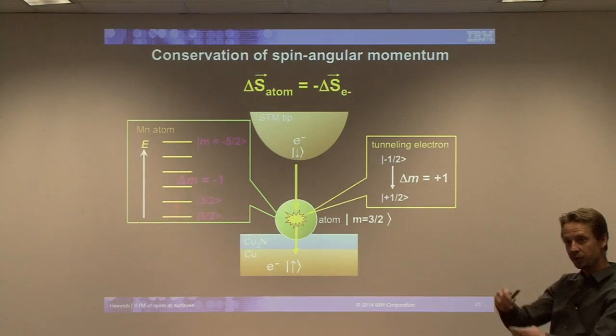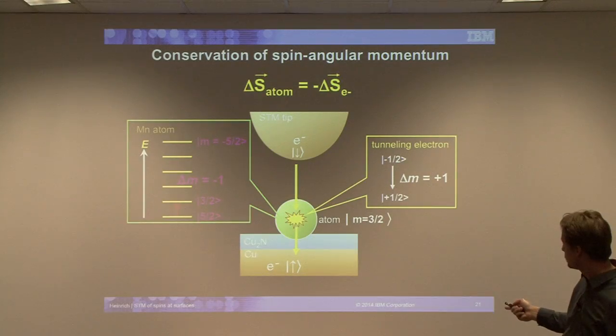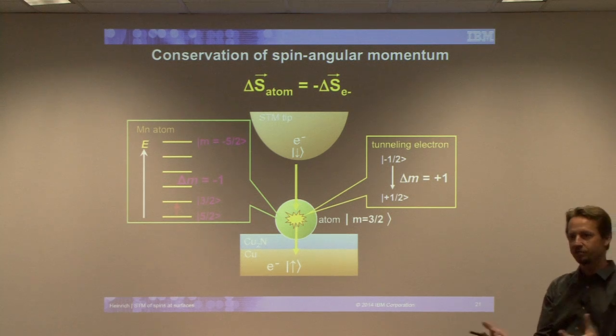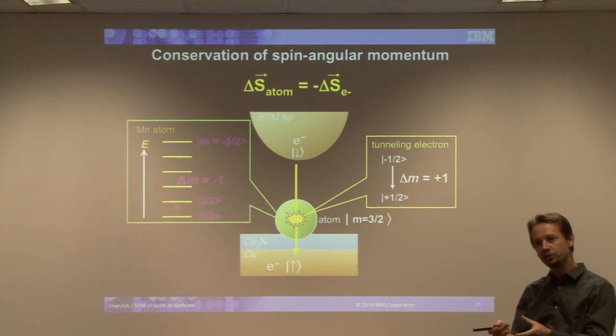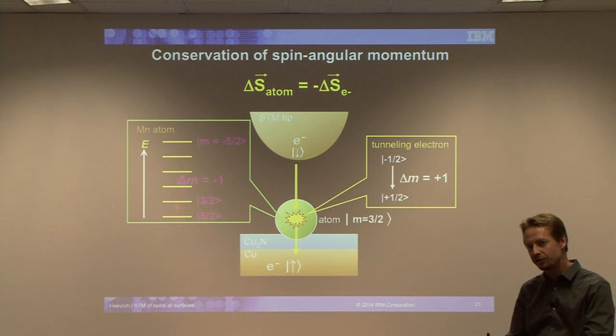We can do it time dependent, right? If we kick this guy out of the ground state, then this will be rotated, if you think about it classically, and your current will change for a short while until it relaxes back down to the ground state. Can you, for example, just pick up another manganese atom trying to change the coercive field or change the total spin for that guy? In practice, the answer is no. But what other people have done is build structures of, say, 5 or 10 atoms on the surface, a big blob of iron atoms, for example, and then those will be a steady magnetic state in a certain direction. They're ferromagnetically coupled to each other. And then you could have this. If you could transfer that to the tip, then the answer would be yes. But that doesn't actually work that way.